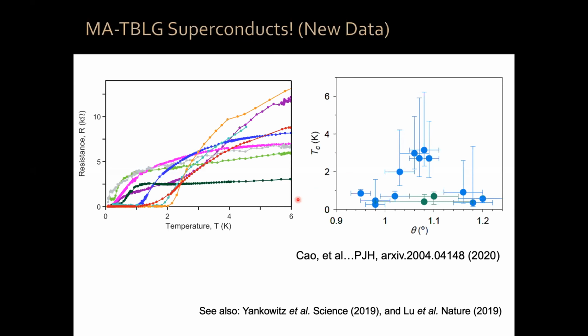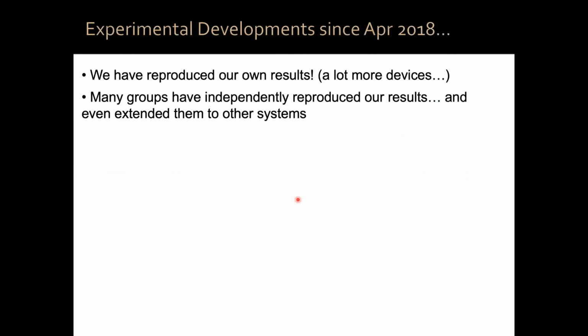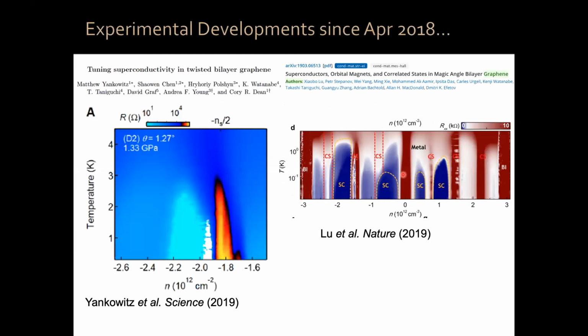More important than you reproducing your own results is when other people reproduce your results. By now, many groups have independently reproduced our results and extended them to other systems and in interesting directions. The first two papers to reproduce our results were by the group of Cory Dean and Andrea Young, where they were able to reproduce our results and tune the superconductivity also with pressure. And the second report was by the group of Dmitri Efetov, who saw additional superconducting domes and a richer phase diagram.